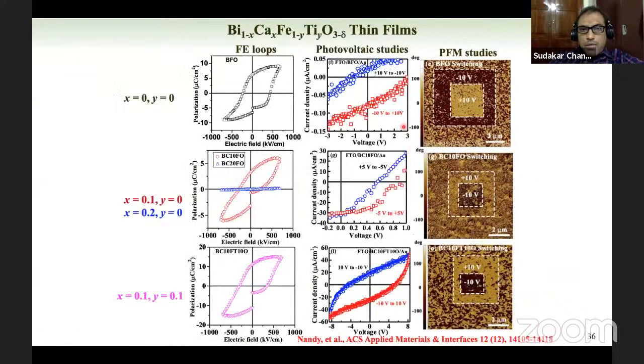More interestingly, as I mentioned at the beginning, bismuth ferrite is both ferroelectric and ferromagnetic. The ferroelectric property can be seen from the ferroelectric loop we have measured on these thin films. And you can also show that by polarizing and switching the polarization, you can change the ferroelectric nature of the particles. Okay, so here is the example. A small region is chosen, and you put a high negative voltage bias, and then you orient the ferroelectric domains in one particular direction, and the other part, you can switch it by applying positive bias.